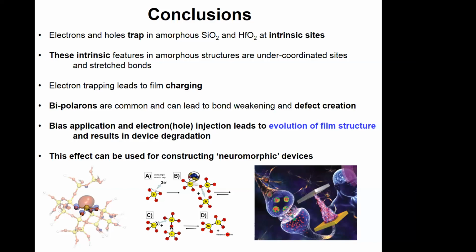Usually we do something like 50 different cells, or in some cases several hundred or thousand, in order to get the right distribution of defect properties. If you have good statistics, at the end of the day, you see that it is more or less Gaussian. But if you don't do it, you may get very unphysical results if you just look at one system. Okay, thanks, Alex.